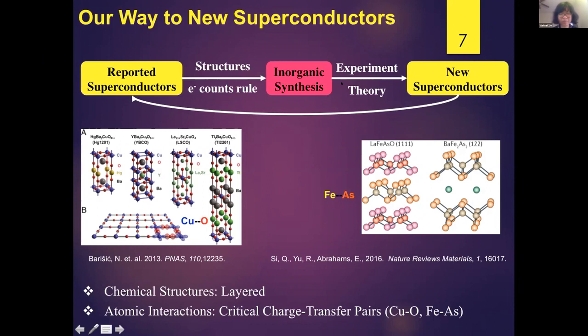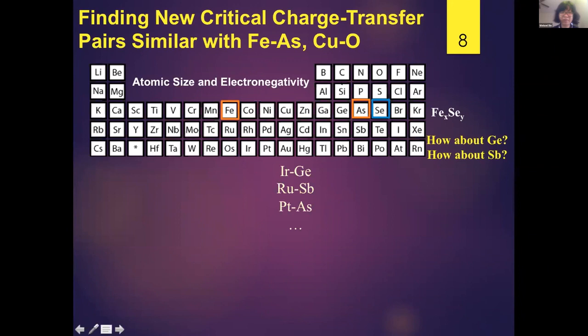So copper and oxygen are like a favorite pair for high-TC superconductors. They just like each other, okay? And iron arsenide is the same. If you change the iron to other elements, for example cobalt or manganese, it's not a superconductor. So what we can see as chemists is that our intuition tells us this specific atomic interaction is very important, and we call it a critical charge transfer pair. Like copper-oxygen and iron-arsenic. So if we want to find a new superconductor, especially a new high-TC superconductor, what can we do?